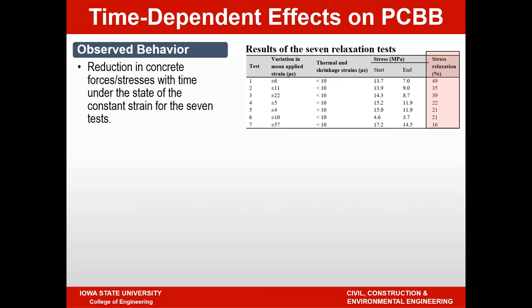And then you can see the stress applied at the beginning of the test and at the end of the test. Most importantly, you see in the right-hand column the change in stress due to relaxation varied from as much as 49% in the very first test to 16% in the last test, which was the older specimen. So obviously, the older the specimen, the lower the relaxation, the lasting force or stress is going to be.